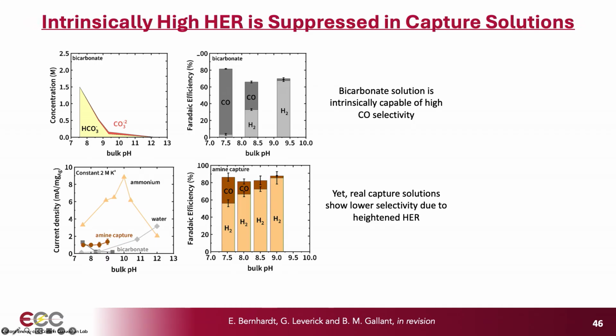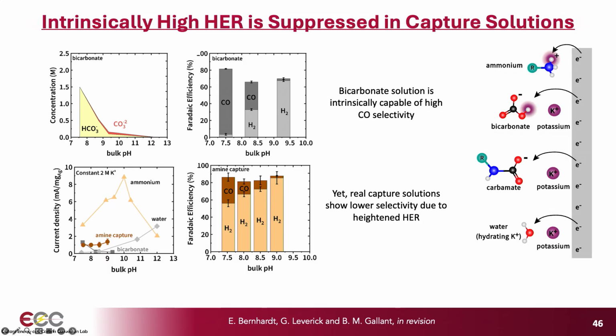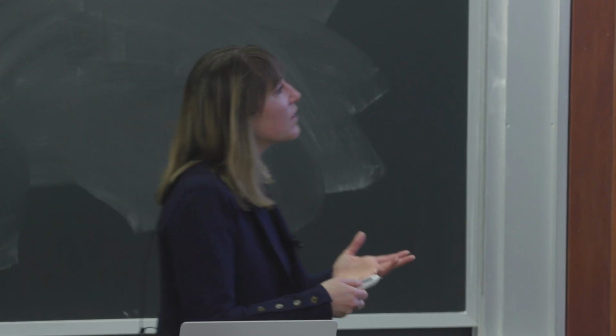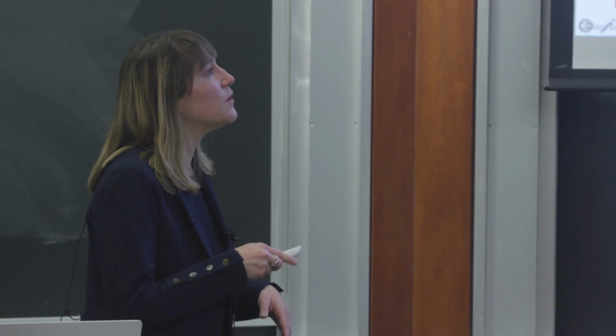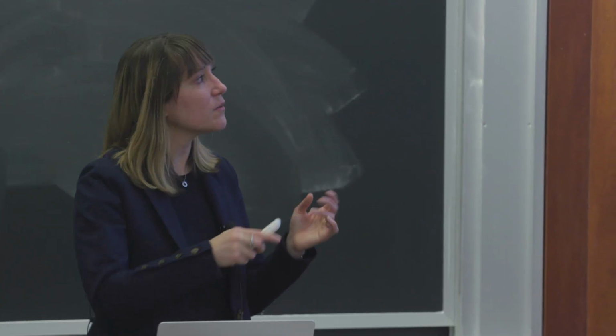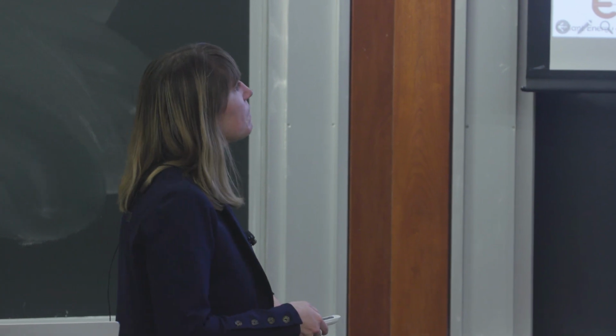I think the bright spot here is that if we look at the overall activity in the ammonium-only systems, it's actually quite high. But in the capture solutions that contain this multitude of different species, it's already mitigated quite a lot. So that tells us that there are species that are outcompeting the approach of ammonium to get to the interface. Ammonium is still reaching the interface because we're still seeing higher hydrogen than we really want, but it's much mitigated compared to the ammonium-only conditions. So this points a path out for us: if we can figure out how to sequester the ammonium in the bulk solution, or block or competitively outcompete its adsorption at the electrode interface, we think that that's the path to higher selectivity.